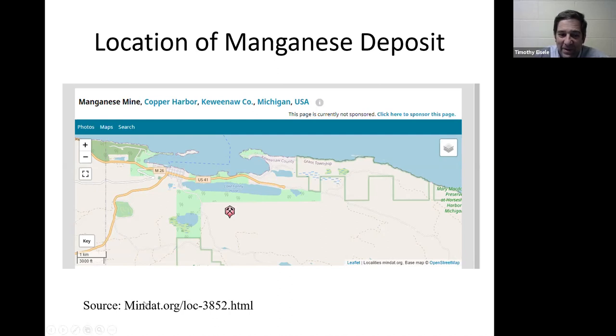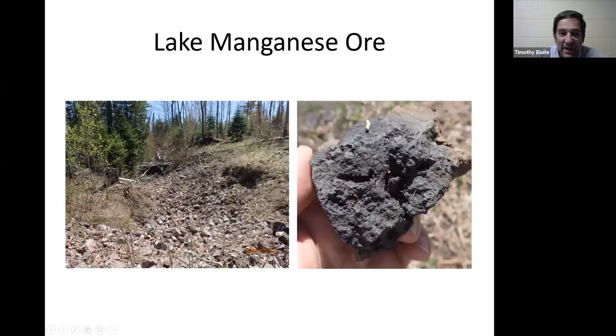And I was able to locate it through the Mindat site. So if you go to Mindat.org, location 3852, you'll get this map and it'll show you exactly where it is. And if you go there, you can still see the remains of the exploration trench where they dug it out. And you find these black electrically conductive rocks, which are manganese dioxide. So we actually have something available that I can use as an actual ore for evaluating this process.